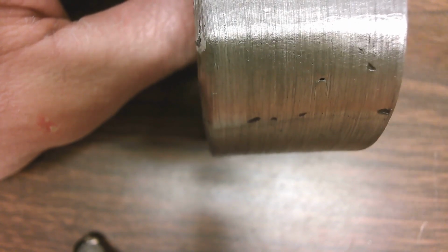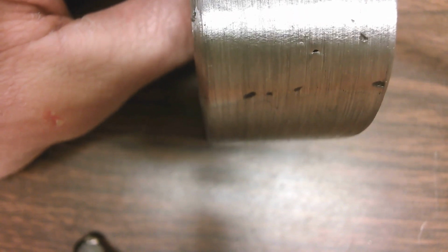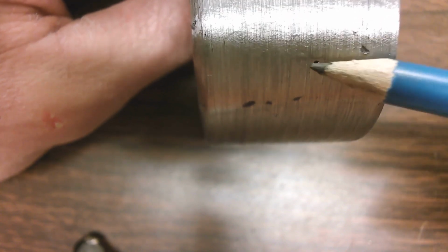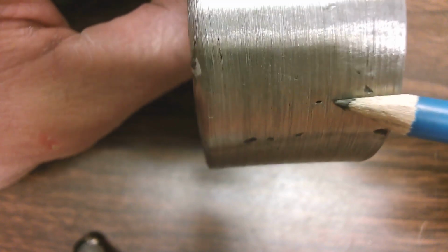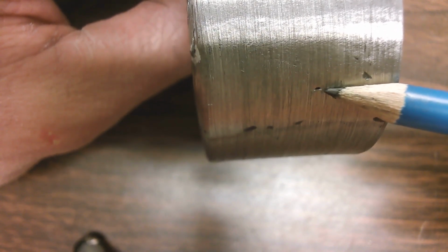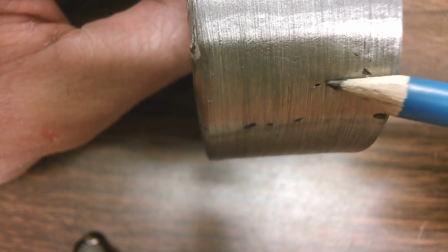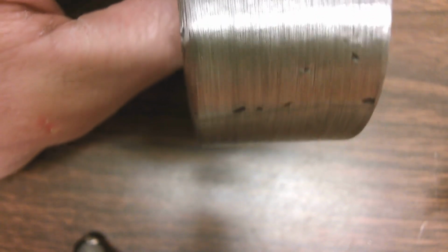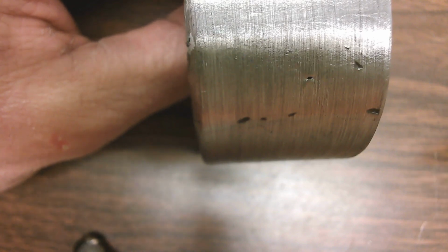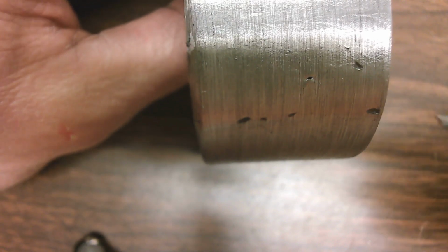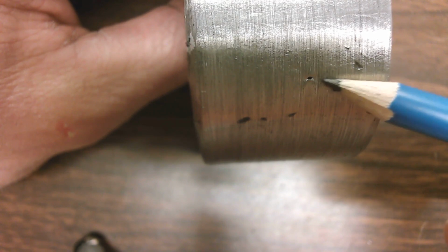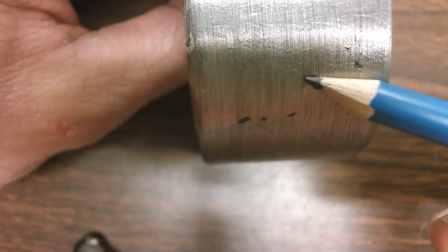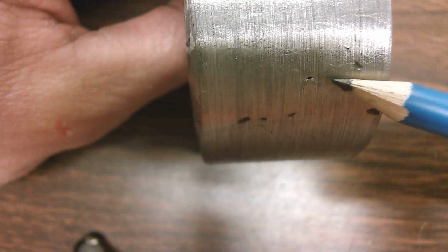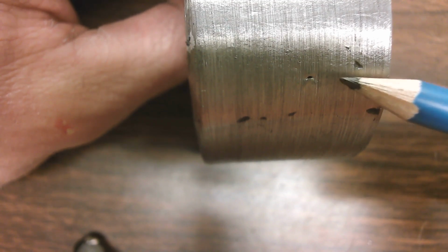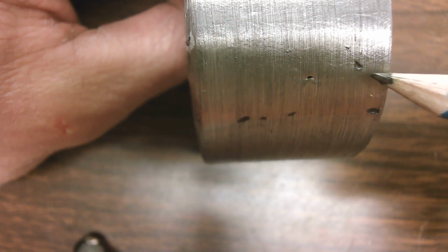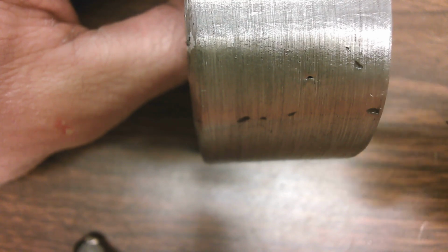But again, all those checked out prior to bending. They're all less than a 32nd of an inch. There's only one discontinuity we have right here after the bend that actually popped open, and there's a little tiny hole right there. And I did take a magnifying glass, put it on there. You can see a little tiny itty bit of slag. But again, we're looking at that, and clearly it's right about a 32nd of an inch when I measured. So a 32nd of an inch is that threshold. If it's less than a 32nd of an inch, then we don't count it at all.